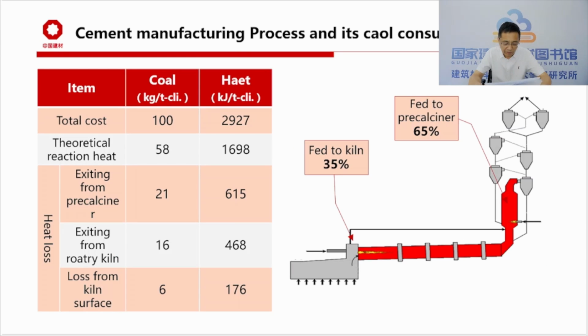Fuel for cement clinker burning is mainly coal. Roughly 100 kg of coal is needed for 1 ton of clinker burning, with 35% of coal fed into the rotary kiln and 65% into the precalciner. It must be noted that the theoretical heat consumption for clinker formation is only about 58 kg of standard coal per ton of clinker. The rest is wasted on the kiln surface or exits with flue gases.